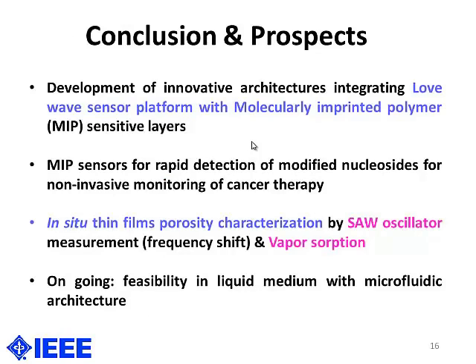To conclude, we have found some interesting and promising results concerning the use of the acoustic Love wave platform combined with molecularly imprinted polymers as sensitive layers for the final detection of target biomolecules as biomarkers for the non-invasive monitoring of cancer therapy. And we have seen that we had the possibility to characterize in situ the film porosity by using the SAW platform and during the sorption and desorption of typical vapors.